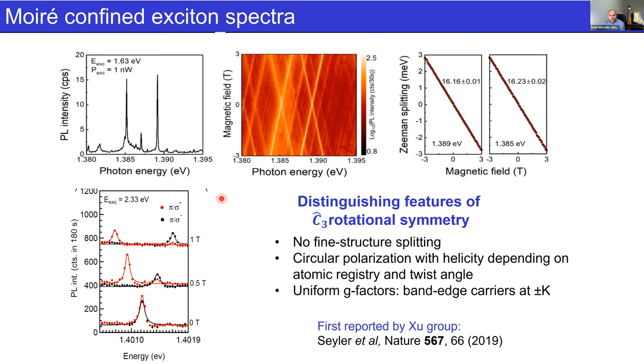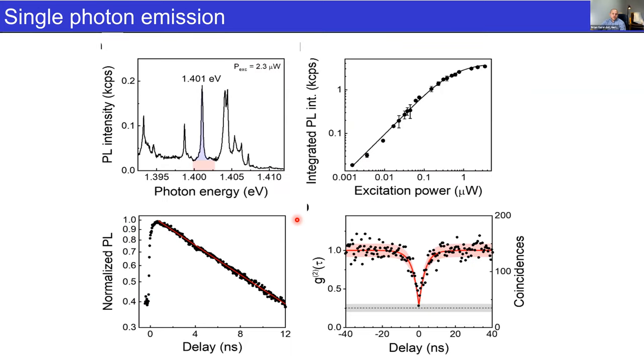So our results are in agreement with the first result from Xu's group. And we probed it a little bit more and engineered the states by adding extra layers as well. So perhaps an opportunity for quantum engineering. And these features that we observe are really distinguishing features of the Moiré superlattice. So it's not expected to arise due to a defect. And we can further probe these. So I should admit these states are not bright. So we can search around for an isolated single emitter and filter it and do lifetime measurement and a Hanbury Brown and Twiss anti-bunching experiment to see if it's acting like a single quantum emitter. And indeed, we can get anti-bunching below 0.5, indicative of a quantum emitter. So it confirms the quantum nature of these trapped excitons.